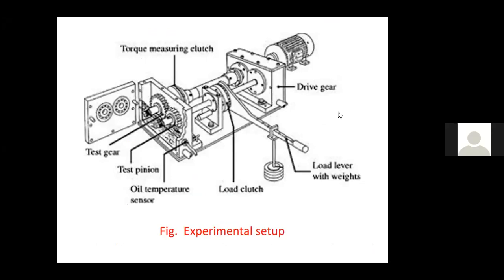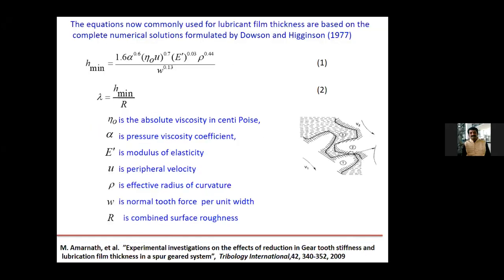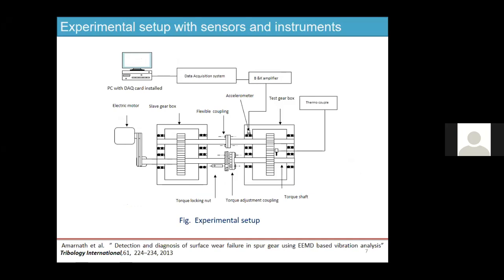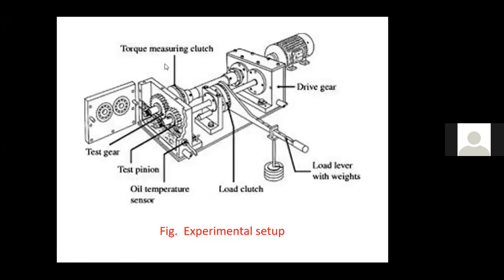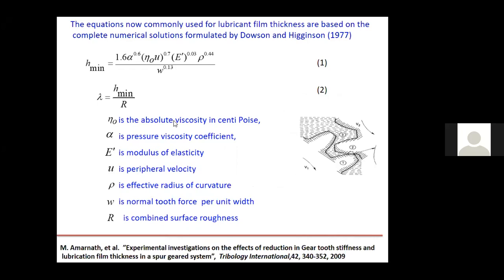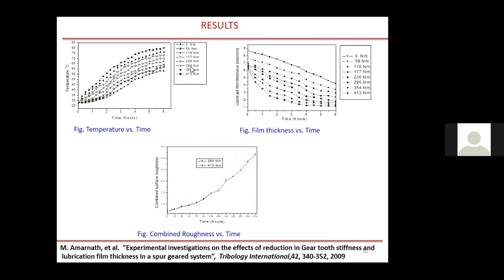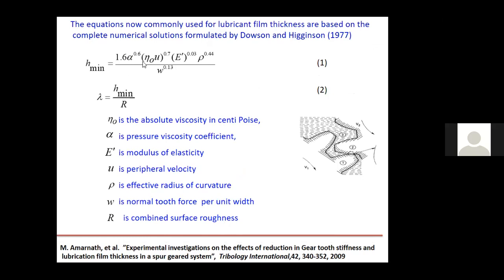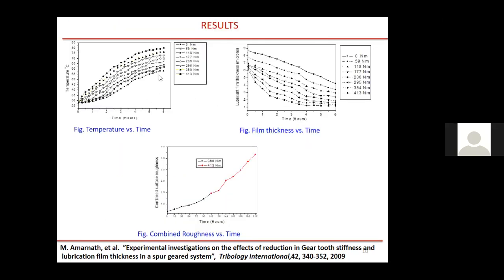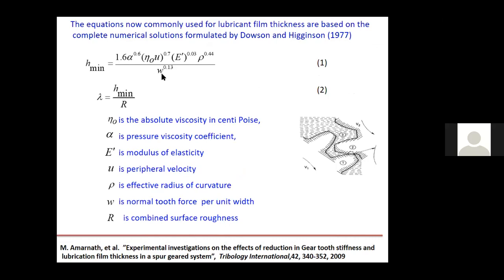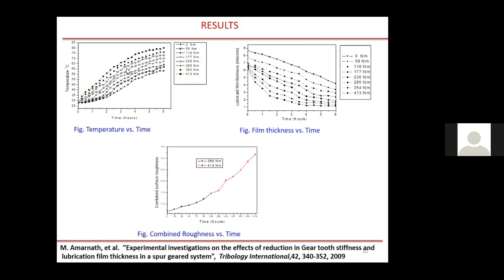Okay, fine. So this is a special type of gearbox used to estimate lubricant film thickness using this Dowson equation. The experiments were carried out by considering 8 loads, from 0 to 413 Newton meter torque load conditions. As we increase the load, temperature is increasing. So we can estimate lubricant film thickness by using Dowson's equation. Here the only changing factor is load.